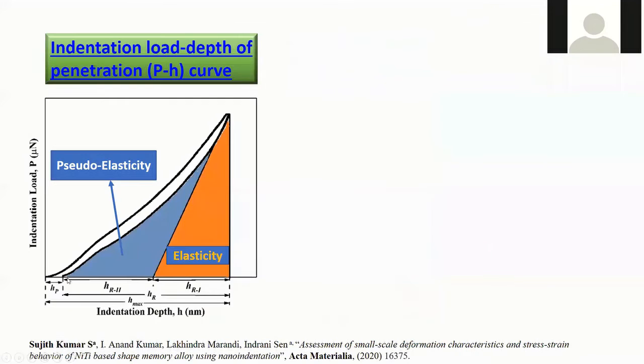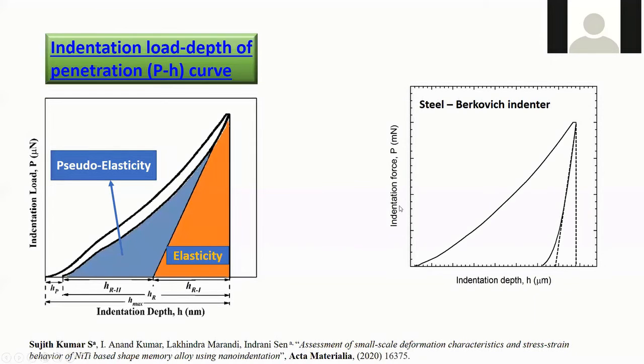Okay. And for each of these grains, this is again a representative indentation load versus indentation depth curve, which is what it is supposed to be for a nickel titanium alloy. This one is for the case of steel, where we can see this is the typical P-h curve. P means indentation load and h signifies indentation depth. And in comparison, this is for the nickel titanium. You can see that this is completely different from that of steel, right?